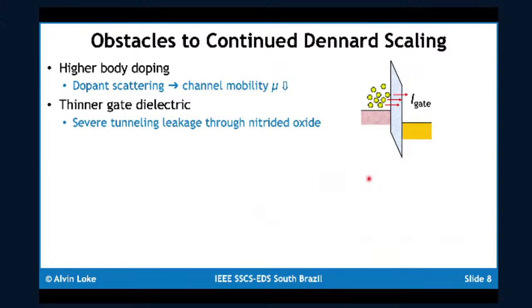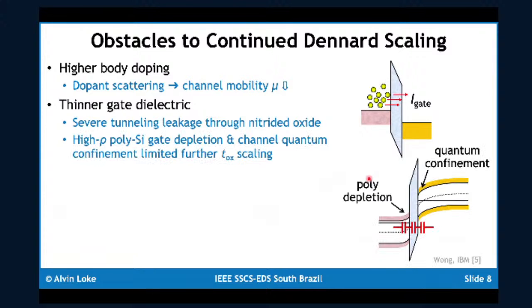Furthermore, as we're thinning the gate dielectric, we've been experiencing severe direct gate tunneling leakage through the nitrided oxide that historically has been used. Further, with the polysilicon gate not being a very good conductor, we actually end up with gate depletion in the polysilicon gate, which moves charge away, and also quantum confinement due to the high doping concentration, where you've got essentially limitations in density of states.